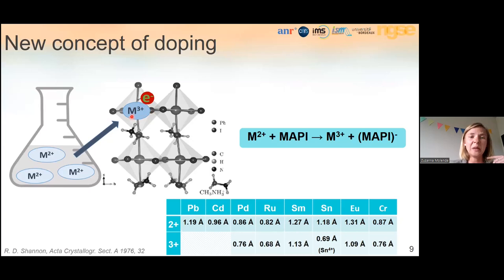Today I present results for samarium. In the first experiment I mixed the perovskite precursors together with samarium diiodide, spin-coated and annealed them, and measured the lateral conductivity with symmetrical gold electrodes. I observed a slight increase of conductivity — up to nine times — but also a big spread of results. We suspected water contamination in the lead precursor since samarium iodide is very reactive and doesn't tolerate moisture.